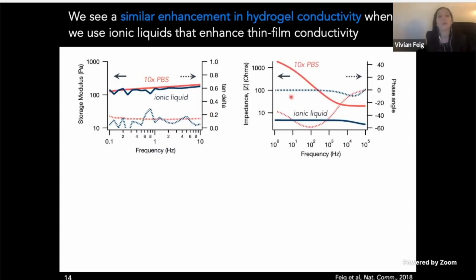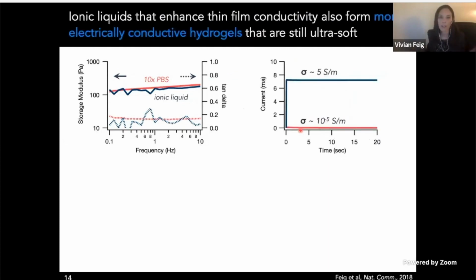But now if we look at the AC impedance spectra of the ionic liquid form gel, we have this really low frequency independent impedance with a phase shift of about 0, which indicates that now, even at this low frequency range, you're getting electrical charge carriers that can still enable that resistive behavior throughout the entire range of tested frequencies. And taken another way, if we apply a constant voltage across these materials, then now we can sustain a significant current, which enables us to see that these materials have 5 orders of magnitude higher electrical conductivity than their PBS form counterparts, despite having really similar mechanics.